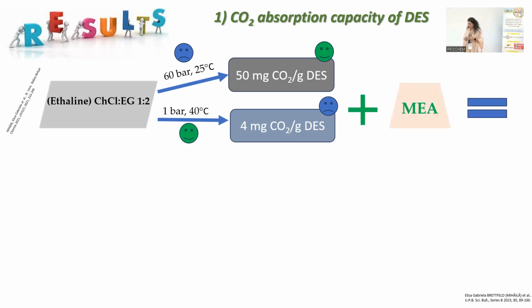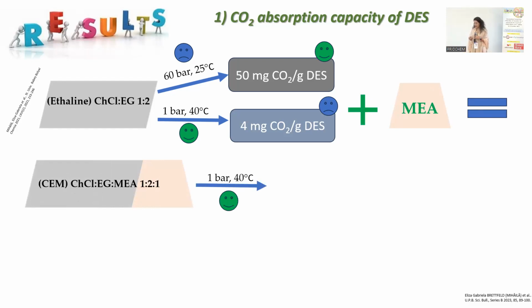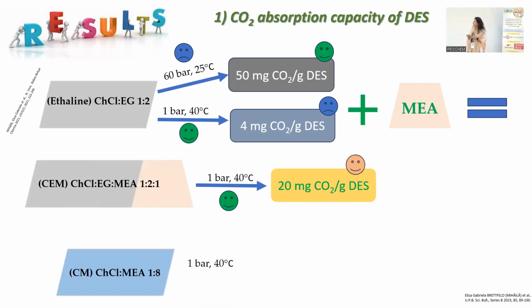Therefore, I added monoethanolamine. We had a ternary solvent. We applied again the green methods, and the result was surprisingly good, just by heating it a little bit.